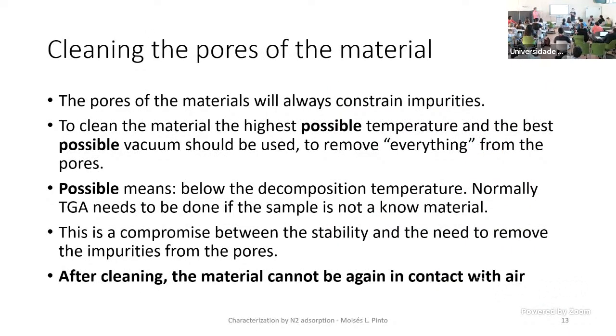So, the materials usually have impurities inside. If it is an adsorbent, everything, moisture, other vapors, and so on, go inside the pores. First thing is try to clean it. How? Using the highest possible temperature, and the best vacuum you can apply, to remove everything from the pores. And of course, possible means that we should avoid the decomposition of the solid. What we want is to remove the molecules that are in the pores without spoiling the surface of the material or even degrading completely the material. This is always a compromise between the stability of the material and the need to remove impurities.